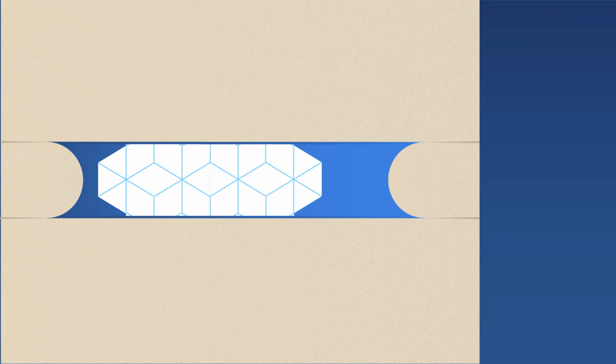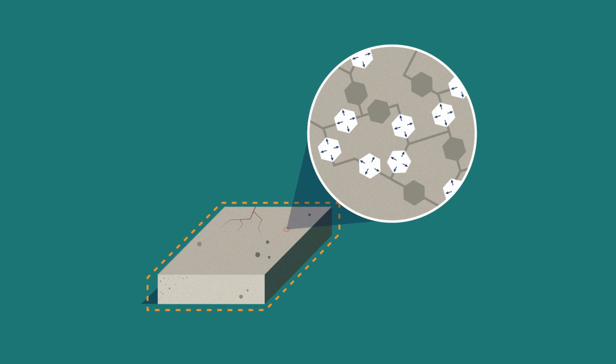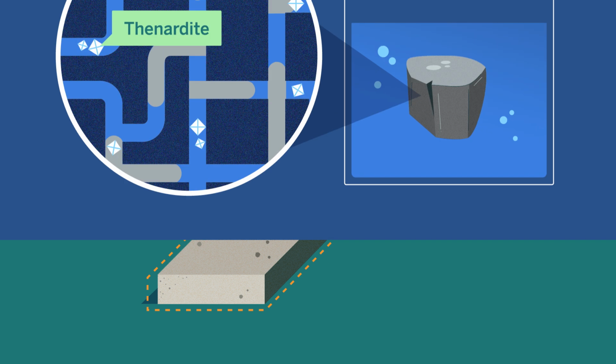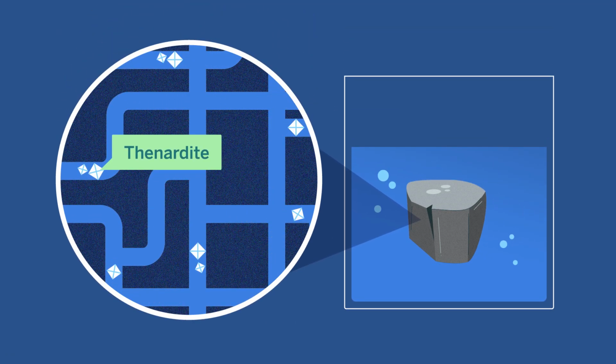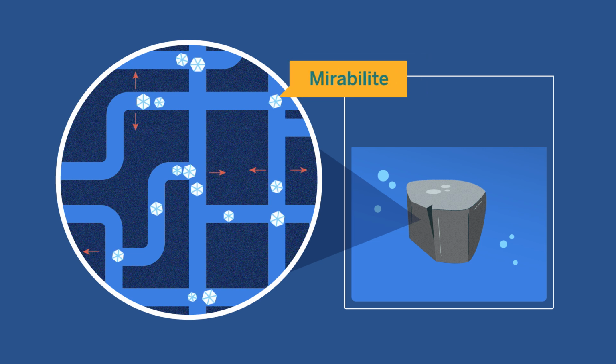When crystallization pressure develops, the risk of damage increases not only with that pressure, but also with the fraction of pores filled with restrained crystals. All those factors combine to explain why phase changes occurring through coupled reactions of dissolution and precipitation, as for sodium sulfate, can be very damaging.